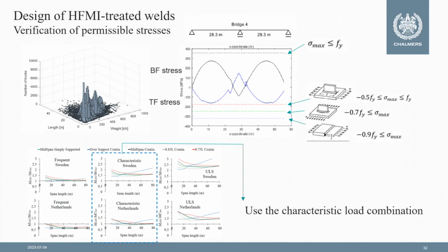For the second question, which is regarding the maximum permissible stress, the same measured traffic data were also used, and they were correlated to the limits that I showed before. It was found that a safe estimation of the load effects, to avoid overloads that would result in relaxation of these residual stresses, could be achieved by checking the maximum load from the characteristic load combination. So that is also specified for that aspect.